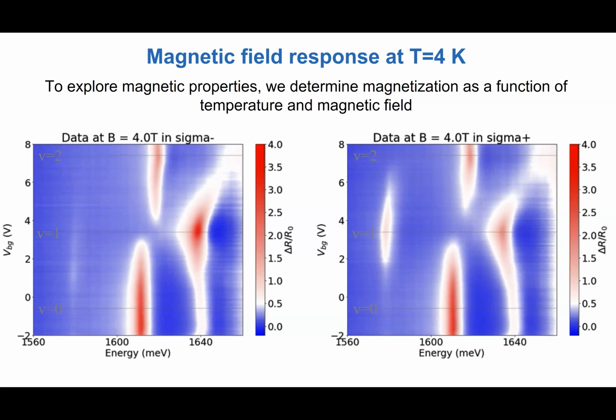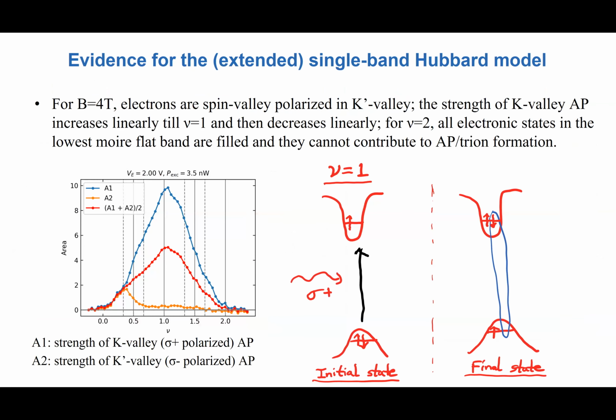So we can use this resonance and the ratio of the populations to determine the spin polarization. And this is how the oscillator strength of this resonance behaves. It increases until I reach filling equals one and then goes down to zero. So how do I understand this? The transitions that lead to this attractive polaron are associated with basically exciting an electron from the valence band to the sites that form this flat band.